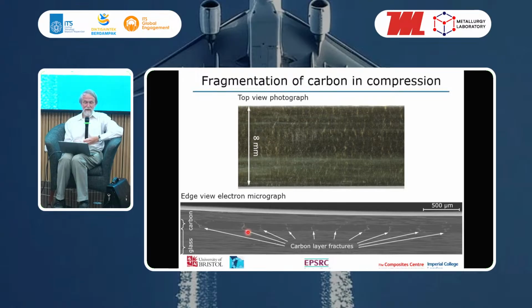So what's happening is that the carbon fibers are breaking in compression, and there's a little bit of local delamination occurring there, which we can see through those yellow marks on the surface, and that's producing a little bit of additional local strain, a bit of pseudo-ductile strain, and is giving us that change in slope that we saw on that previous stress-strain curve.